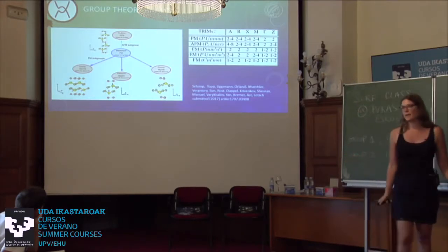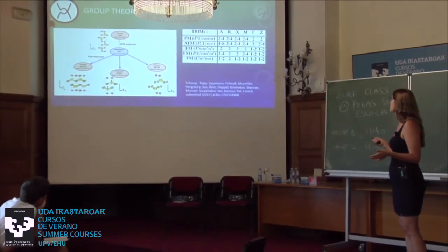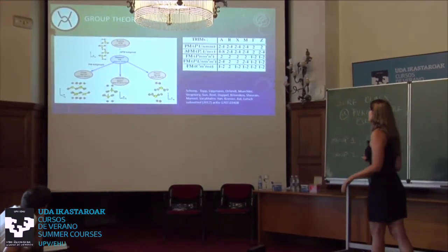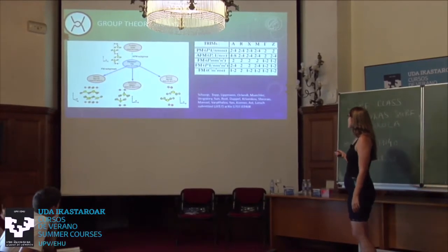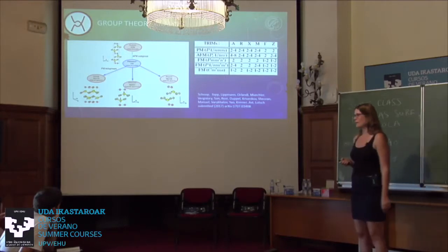And then if you add magnetism, you change a lot of those degeneracies. So there's lots of splitting. You can have only twofolds here in the ferromagnetic cases. But what we liked the most, and was kind of surprising for us, is that she found that there's a possibility of having an 8-fold degeneracy in the antiferromagnetic phase.